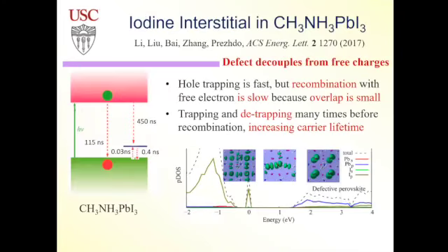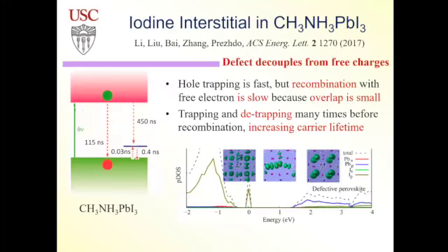This inorganic lattice, so you have lead and iodine. So red is lead and green is iodine. So they're vibrating. And then you have an organic molecule in the middle. So this is the molecule. Could be a slightly bigger molecule, could be actually cesium, one big inorganic cation. This molecule rotates. So because you have inorganic lattice, it's a good conductor. Because people can make solar cells from organic matter, but usually you can make organic light-emitting diodes efficiently because charges can combine, make exciton and emit.